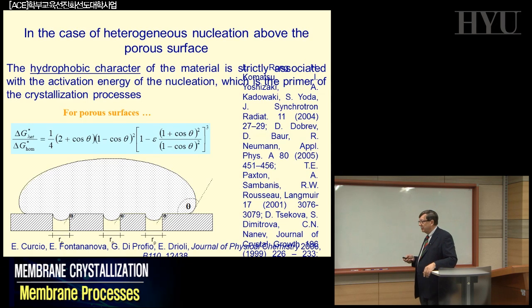Traditional equation that we have been discussing already in membrane distillation is also to be considered, and if you want to understand this variation of the delta G heterogeneous to delta G homogeneous, we already discussed a little bit, and here it's becoming more and more significant because you have to introduce, and this now is an effect directly on the activation energy, an effect related to the contact angle for sure, but also to the porosity, and more than this, just know this, when you have your pore, remember that this is not a flat capillary, you have some other forces which are active here.